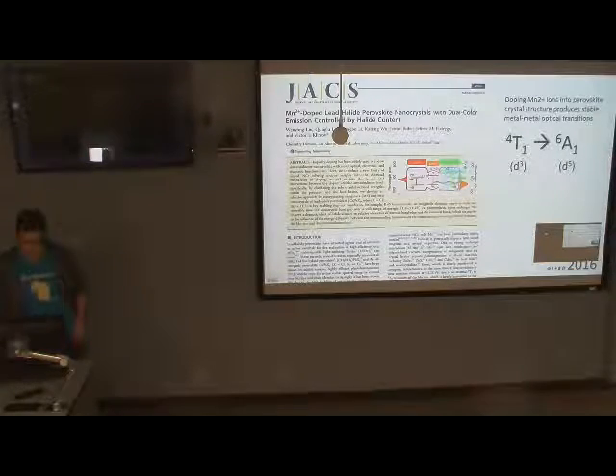And I guess changing the halide would also change the kinetics for non-radiative relaxation and radiative relaxation, because changing the band gap, you change the energy difference between this level of the dopant and the band edge. So smaller energy gap, it's quicker transition to get there because you have less of an energy barrier to hop to that state. And for iodine, it will not emit because the lowest excitation will be intrinsic, not on the manganese.